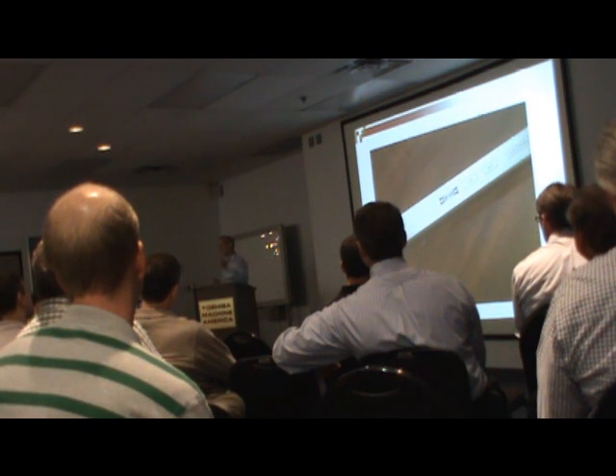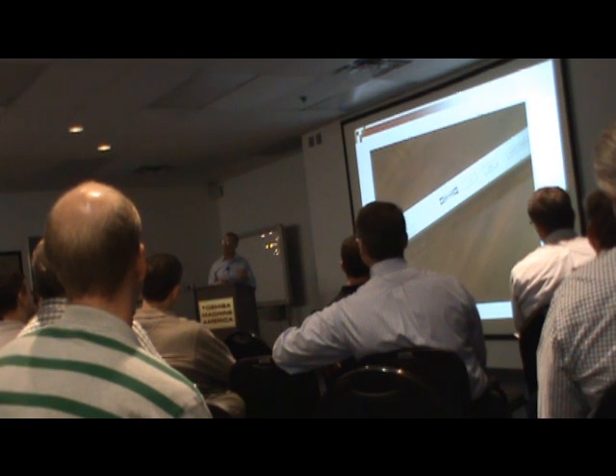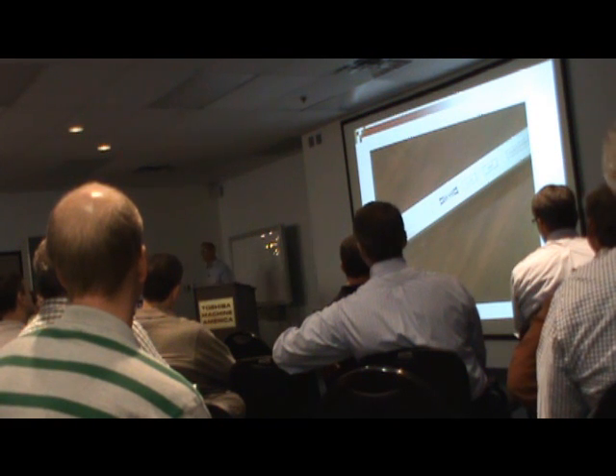We needed to hold this when we processed it within 20 thousandths over that length. It was difficult to do. We got the process. We got the gating done just right. At that time, we didn't have mold flow. We do now. But when they ran their 15 to 20,000 parts in aluminum, they went to a steel tool. The customer did. Sub-Zero is not the customer, by the way, not my customer. So somebody else made the choice to go to a steel tool.